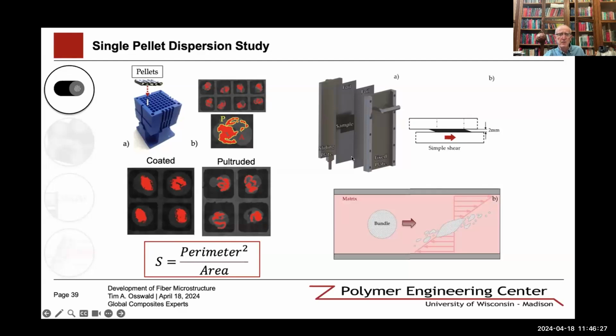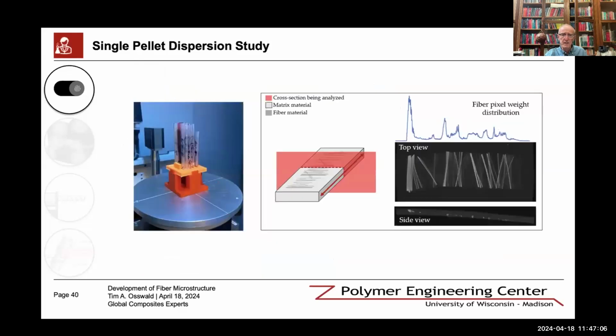So these are the coated compared to pultruded fibers, those are two types of long fiber reinforced thermoplastics. Coated are the ones where the fiber itself is just coated with polymer and extruded. The pultruded ones are the ones where the fibers, no, the other way around. The coated ones are where we have a wax coating on the fiber, and then pultruded are the ones where the fibers already come a little bit more predispersed.